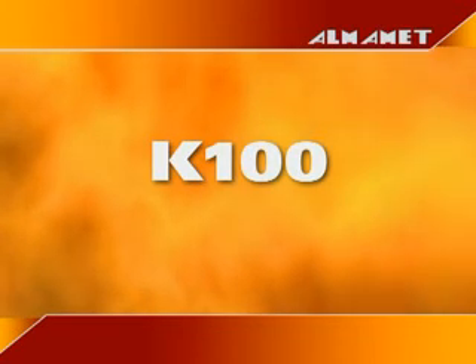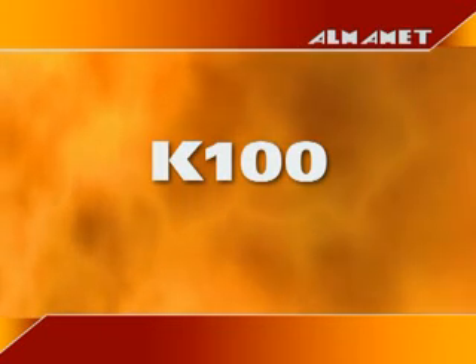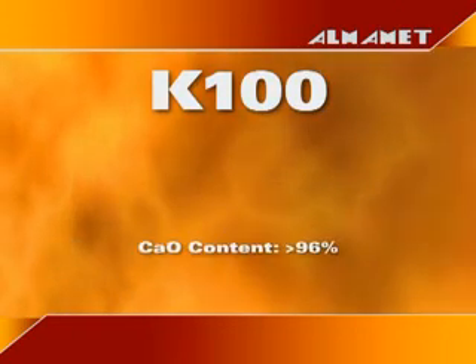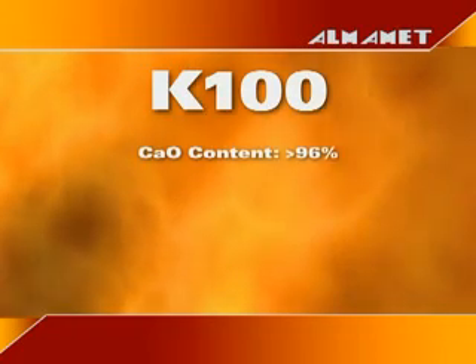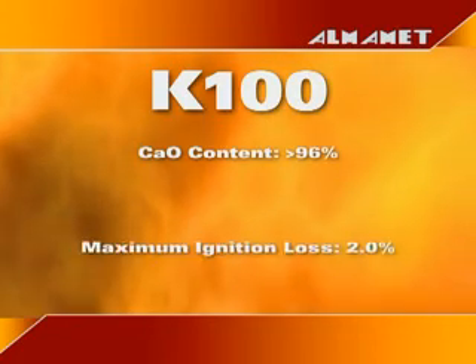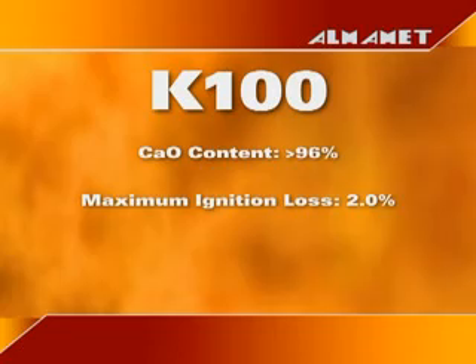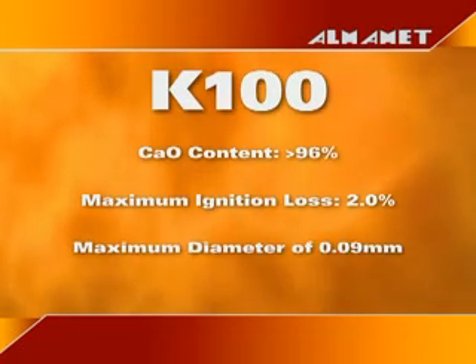Almamet offers different types of prepared lime products. K100 was developed to support mono-injection processes for hot metal and steel desulfurization, as well as co-injection with magnesium. It has a CaO content of over 96% and a maximum ignition loss of 2%, with a maximum granule diameter of 0.09 millimeters.